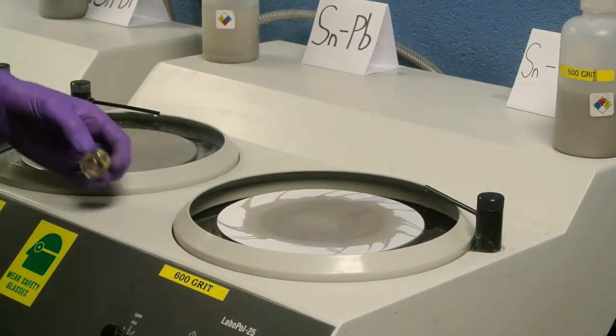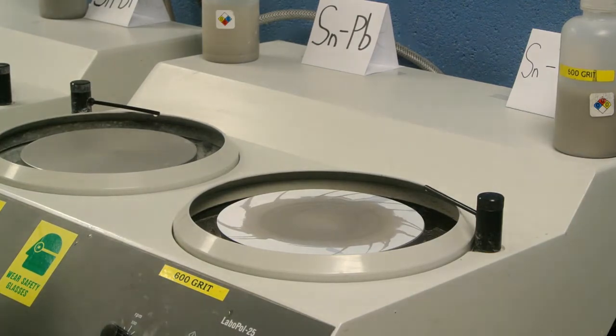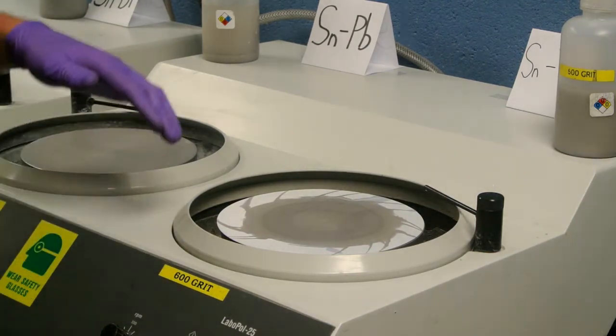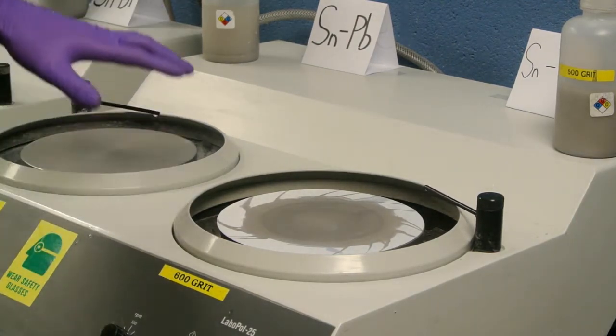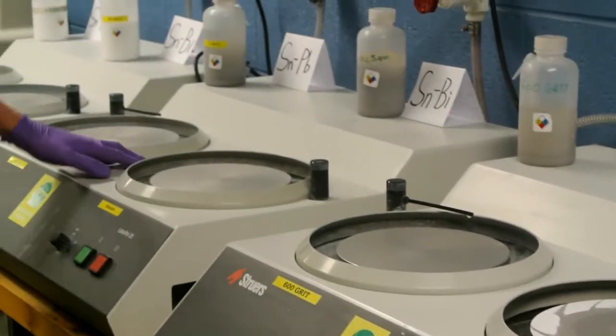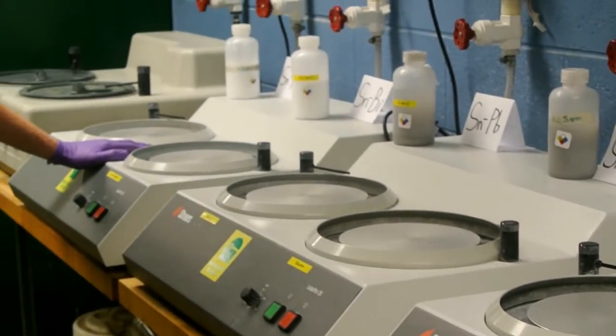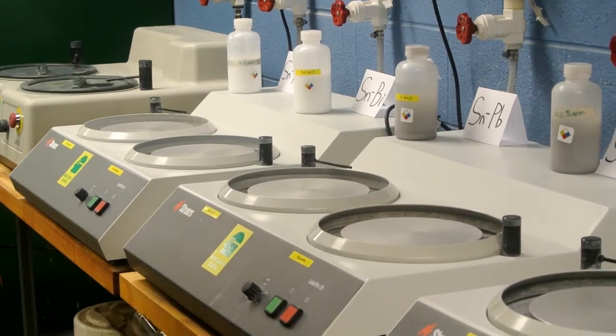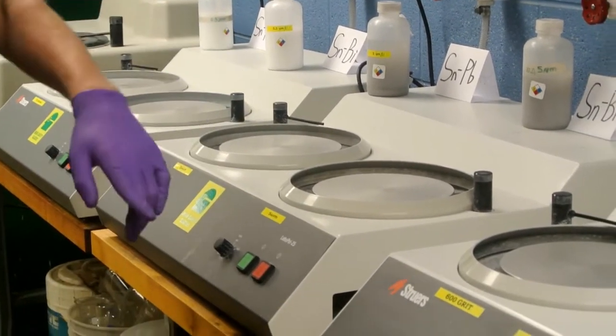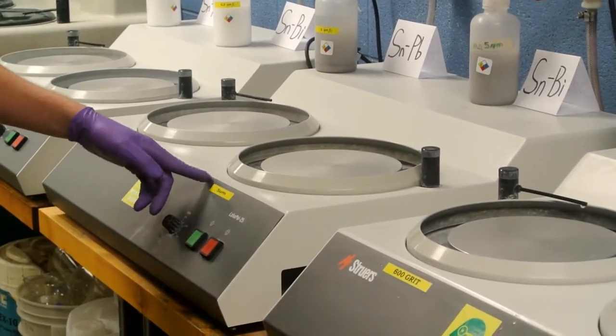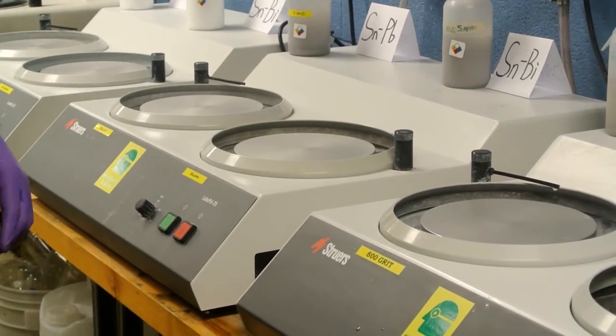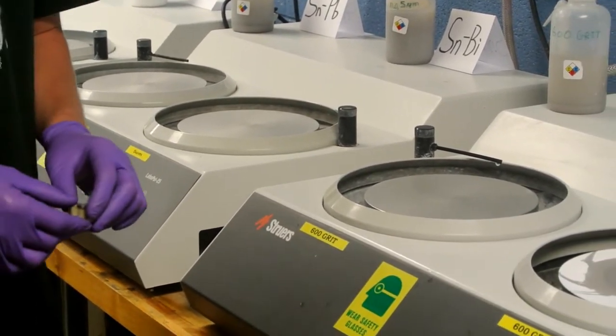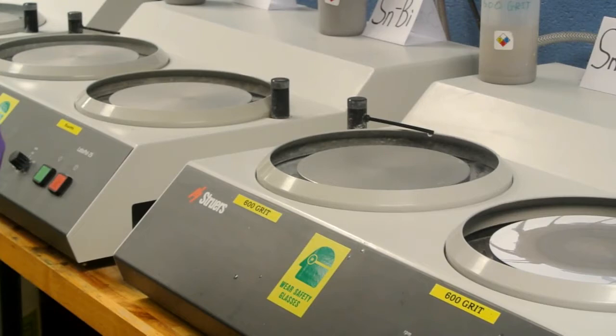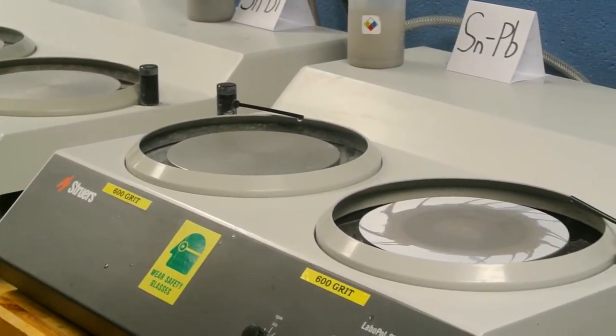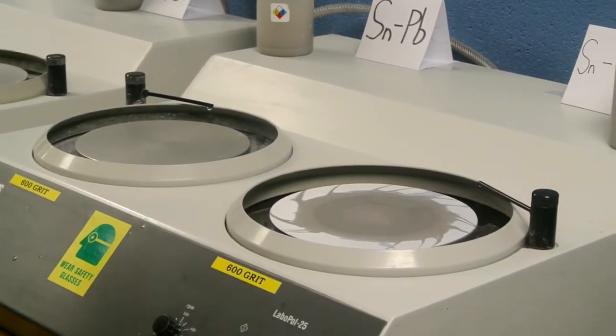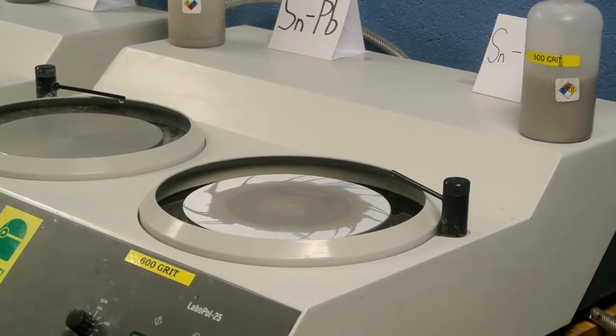So we're almost done polishing using these polishing wheels. Remember, you're going from 600 grit, moving to 5 micron, moving to 0.3 micron, and each time you switch from one table to the next, make sure you're cleaning it like how I said before. It's important to make sure that all the alumina, just as the silicon carbide, is not in the ingot itself.